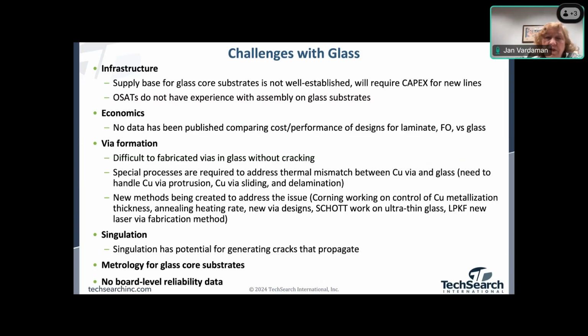Via formation. It's very difficult to fabricate the vias in glass without cracking. You have to have some special processes to address the thermal mismatch between the copper via and the glass. So you've got to handle copper via protrusion, copper via sliding, and delamination. And there's been a lot of work and a lot of progress has been made in this area. So you've got new methods from Corning, SCHOTT, and LPKF, laser via fabrications, a lot of work in the via part, but still more work needs to be done.